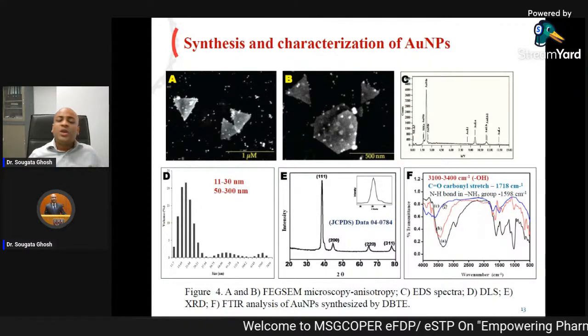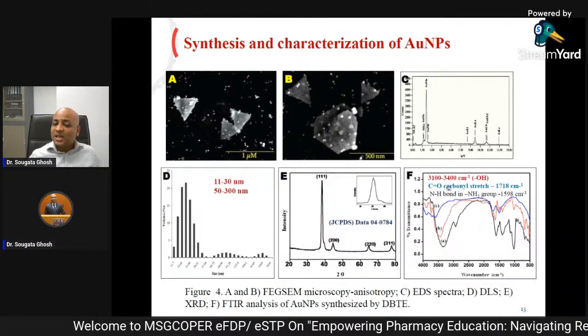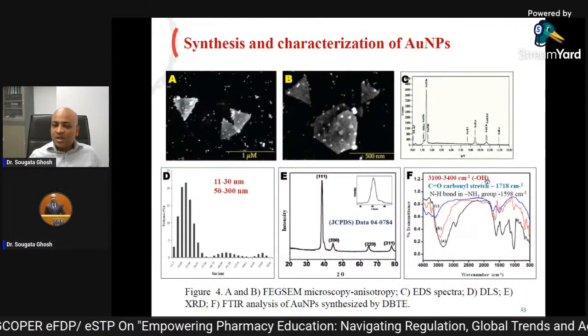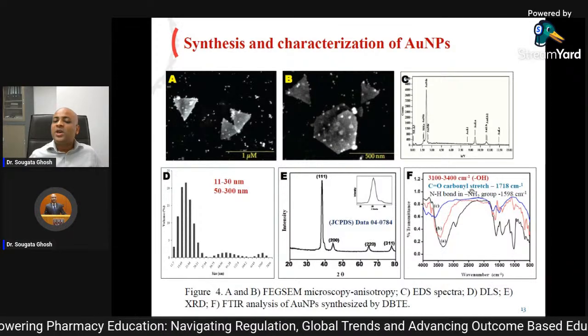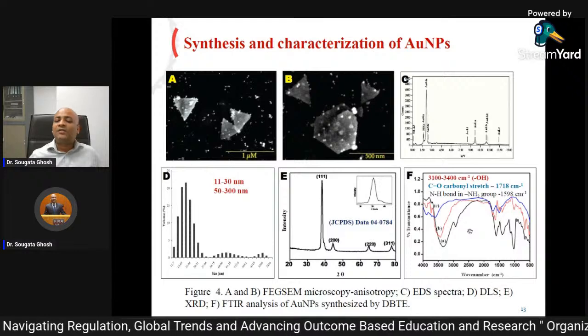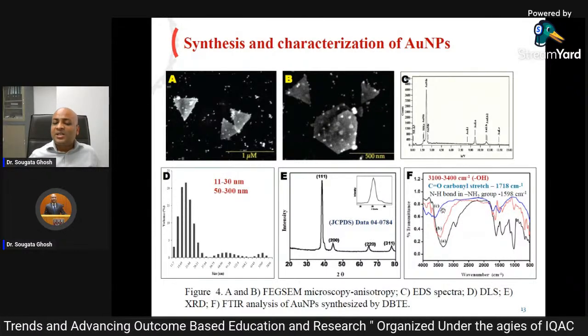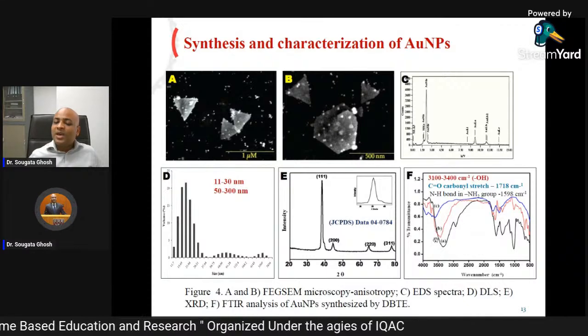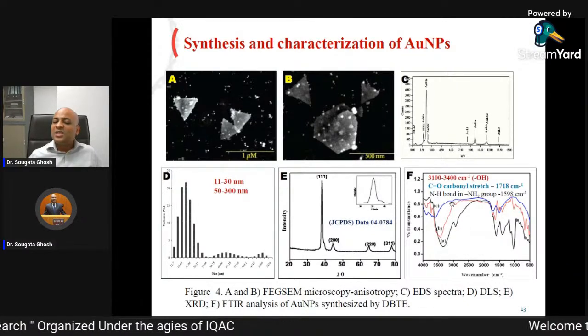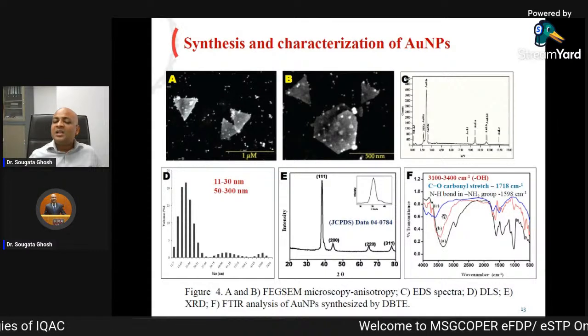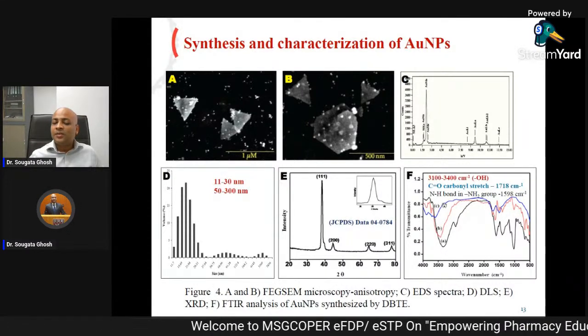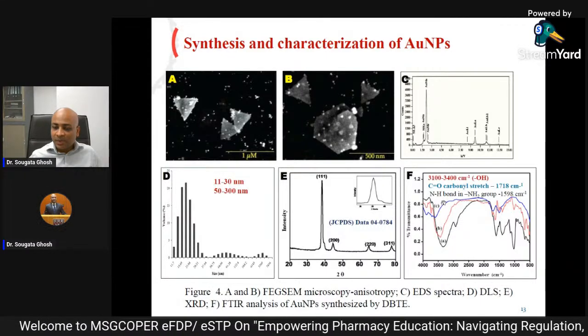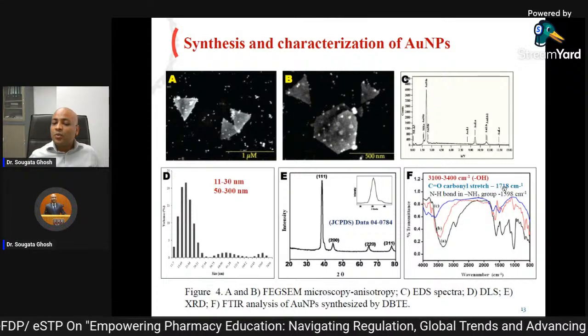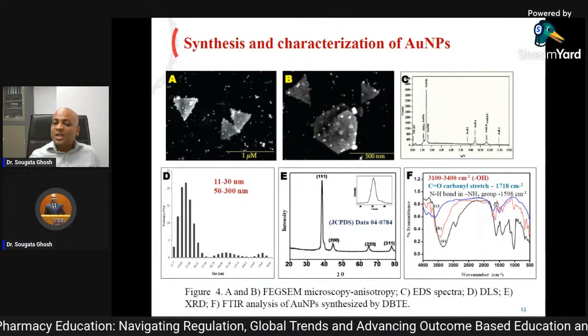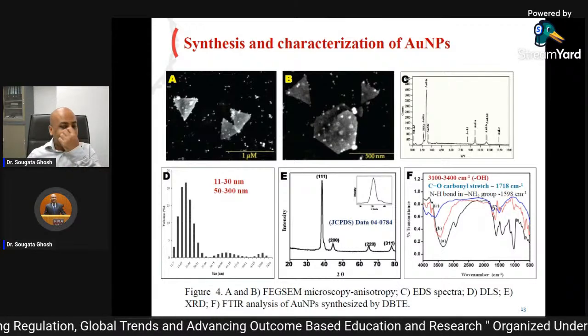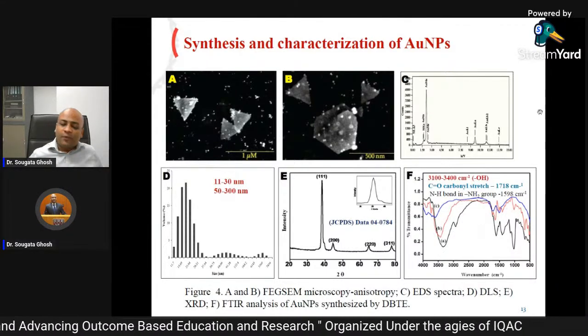We wanted to find out which functional groups are important in synthesizing the gold nanoparticles. And we found this OH group was playing a very important role, because the hydroxyl group is present in phenolics and flavonoids. So these OH groups were decreasing. Can you see over here? This black peak is more in the extract. Then when the synthesis was on, it reduced to this red line, then it further reduced to this blue line. So slowly this OH peak is disappearing, and this carbonyl peak at 1718 was being produced. If you can see, the carbonyl peak was coming over here. And this means that these groups are responsible for the synthesis.